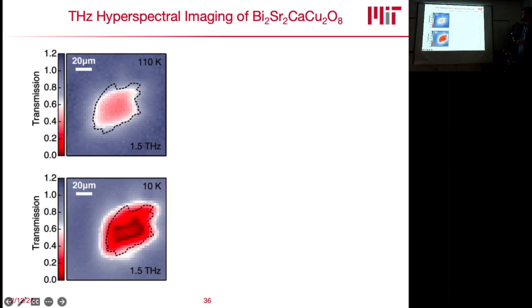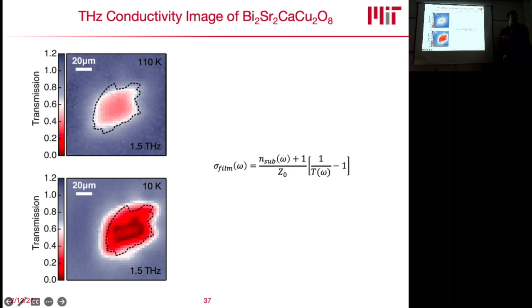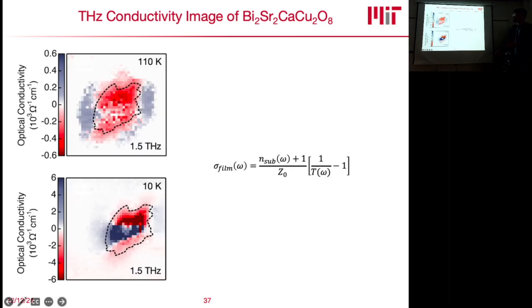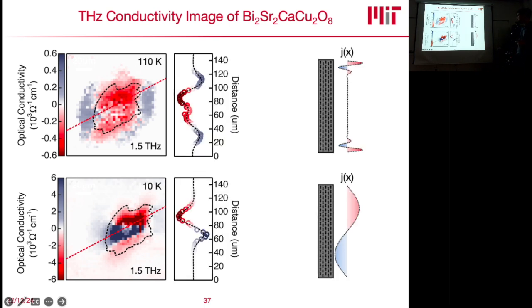And now we can do the same trick. We can take the Tinkham equation and convert every pixel into conductivity, and this is what we did here. This is above TC, so you see an almost homogeneous response inside the sample. Whereas if you go below TC, at 1.5 terahertz, you get this perfect flip between positive and negative, which is what we would expect from a fully expanded plasmonic resonance in this material. This is now shown here as a line cut.